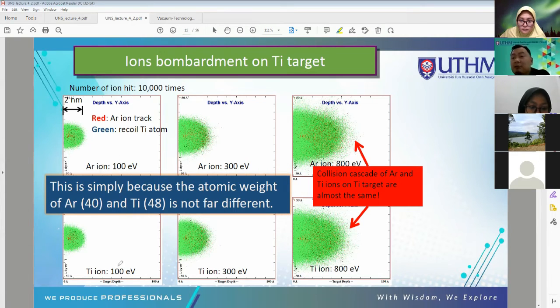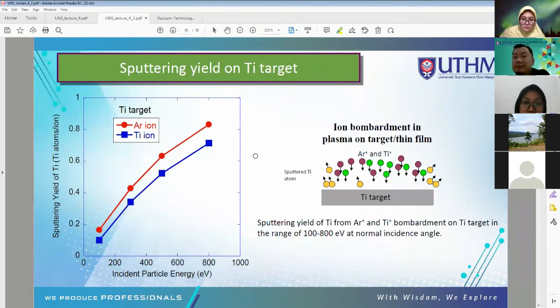Okay, then we try to modify. Instead of using argon ion, what if we use a titanium ion? What's the difference? When we change from argon ion to titanium ion, we can see the trend is almost the same. The scale of the depth of penetration is almost the same, even when we increase up to 800 eV. So the conclusion here is that the collision cascade of argon and titanium inside the titanium target is almost the same, meaning that it can show the effect of self-sputtering in this process.